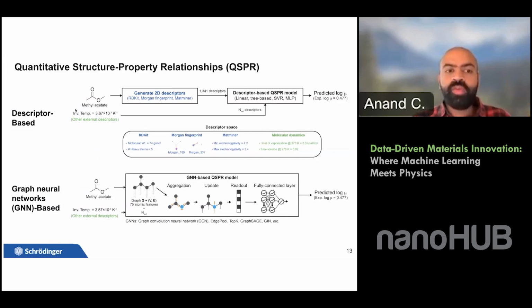So we tried two different models. One is a descriptor-based approach, which is more similar to the AutoQSAR approach, where we generated RDKit descriptors and Morgan fingerprints and also Matminer descriptors for these molecules. And we provided these descriptors to a variety of different machine learning algorithms like linear regression, tree-based regression, support vector regression, and multi-layer perceptron.